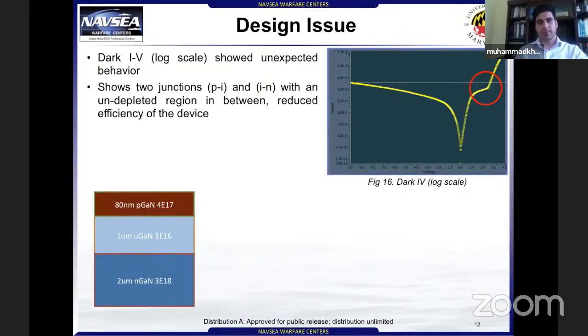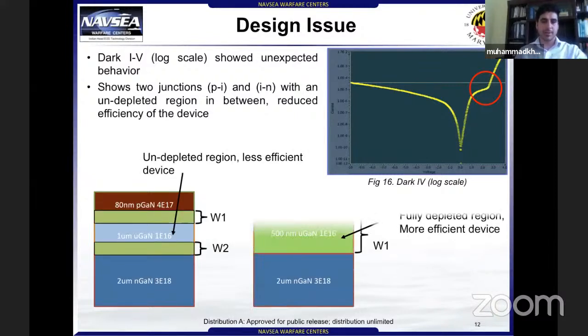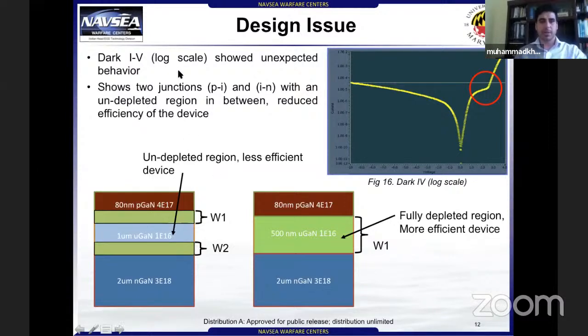We did find a major design issue with our devices. When we did the dark IV in the log scale, we noticed an unexpected behavior. It's shown here. We saw a second bump here, which should not have been there. This indicates that we have two junctions instead of one.